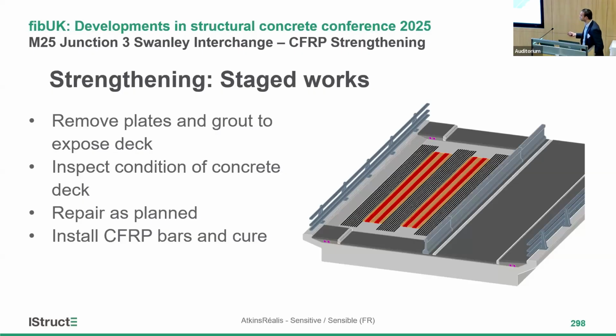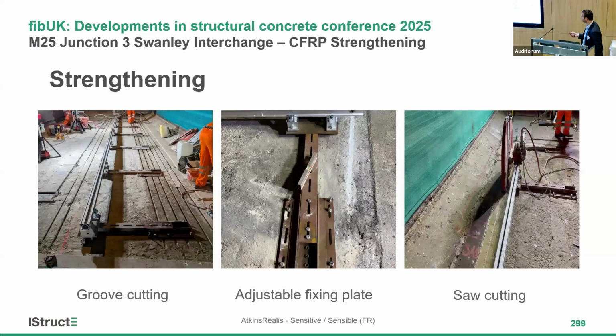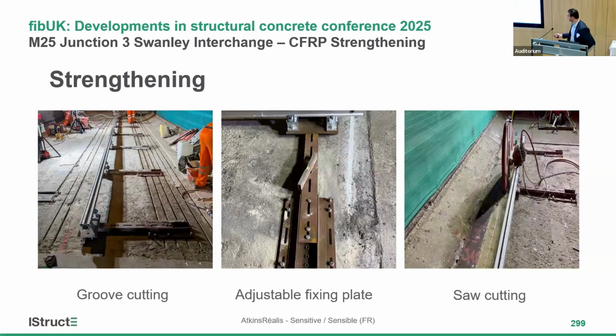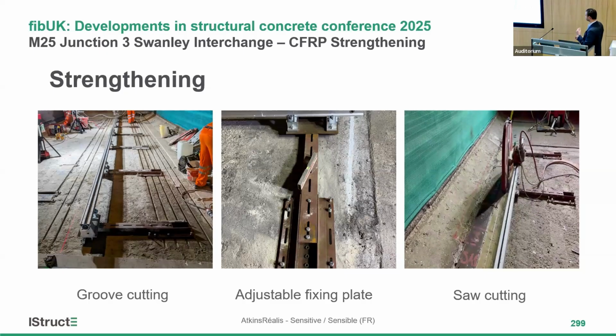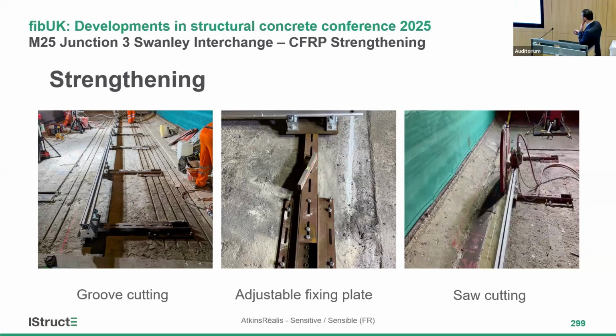So the condition of the concrete was inspected, and then the repairs were carried out as planned in sequence. These are the grooves which have been executed on those specific locations. And it was done using this machine, which was specifically developed for the purpose. If we imagine executing 180 grooves, 14 meters in length, it's quite a bit of an ask to execute these grooves manually. And also we would like to have it as straight as possible, because with any inclination, you create a local stress point in the FRP.